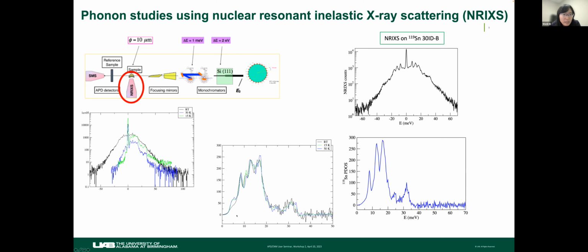Then we found there are some inconsistencies in several spectra because when we cool down, the sample holder also changed position, and it's an unfocused beam, so it depends on which crystals you are hitting. And we saw there is some variation in some phonon mode around 5 milli-electron volts.